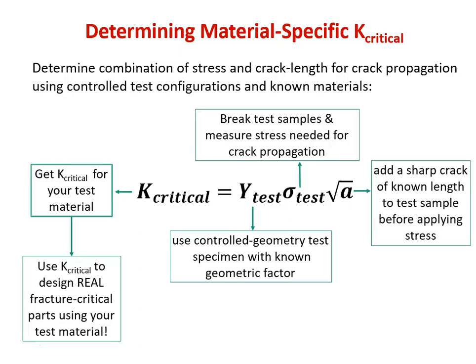Because if it's dependent on the flaw size and the geometry, how did we ever come up with it? And the answer is a lot of testing. Material-specific fracture data is very expensive to obtain. It's not as prolific as yield and tensile stress. When you can find it, you use it.